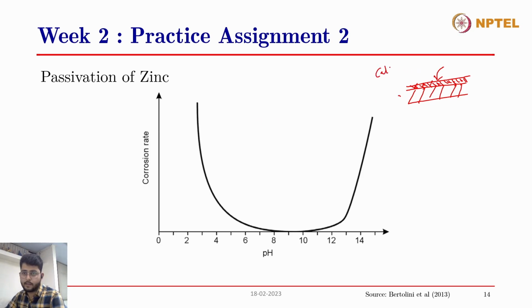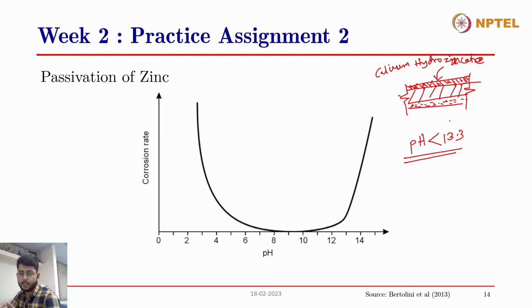This calcium reacts with the pore solution and forms a passivating film, calcium hydroxyzincate. This is the initial corrosion product of the zinc, which acts as a passivating film around the zinc of the galvanized steel rebar, right? And up to a pH of about 13.3, these corrosion products can form a compact passivating film around the rebar. Below the pH of 13.3, the corrosion products will be finer in nature, and hence will not form a well compacted layer around the zinc.